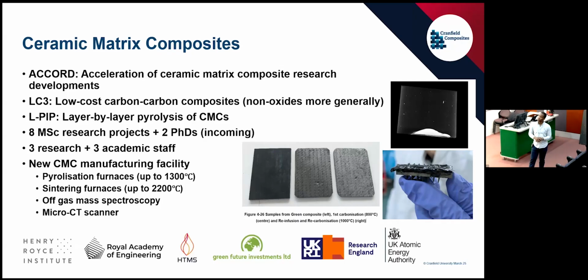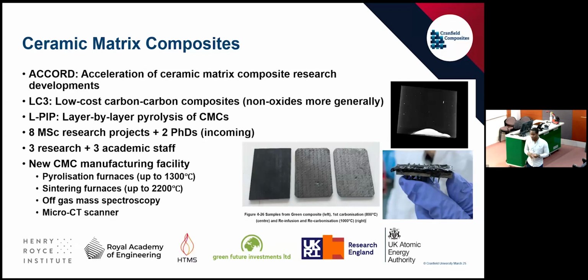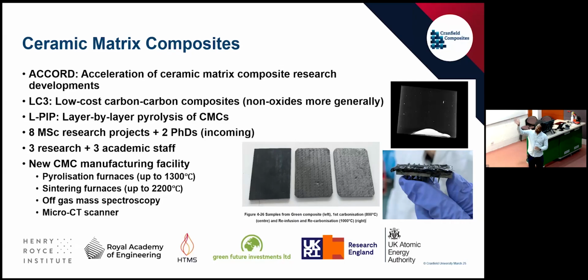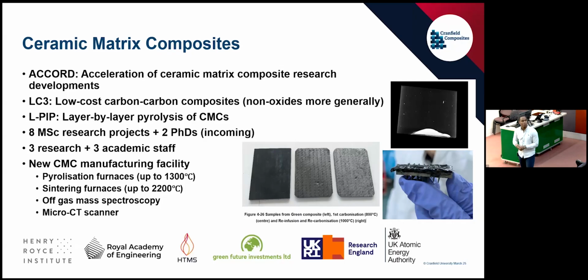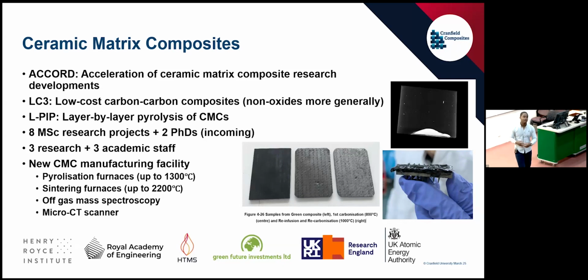And then lastly, there we have a new CMC manufacturing facility. We just invested in pyrolyzation furnaces that go up to 1,300, and sintering furnaces that go up to 2,200. Still quite small, not even half a meter, quarter meter kind of size specimens. But the plan there, along with this micro CT and the mass spectroscopy, which we do have, is to approach national level funding for a much larger facility, as it doesn't really exist in the UK. Actually, no, it does exist, but it's behind significant paywalls. So for academia, this becomes quite difficult.